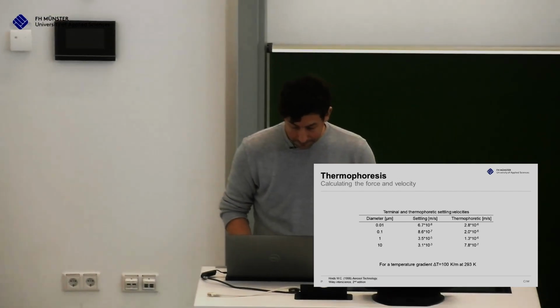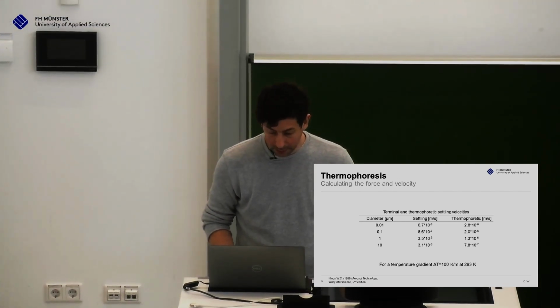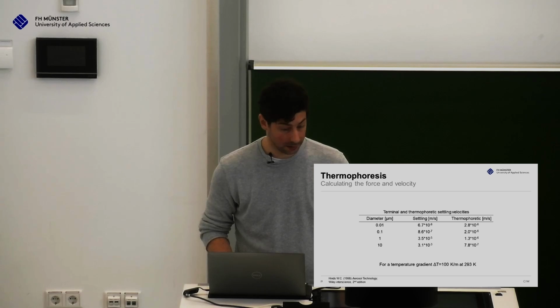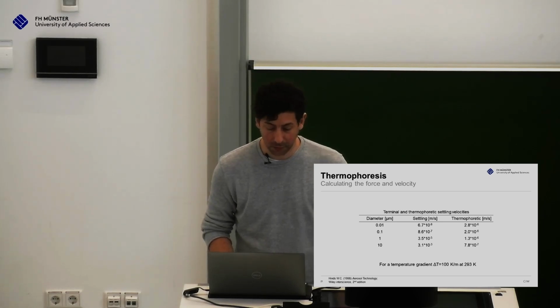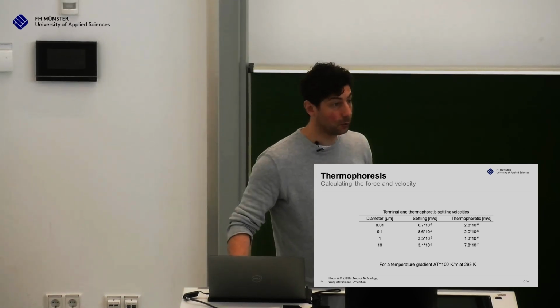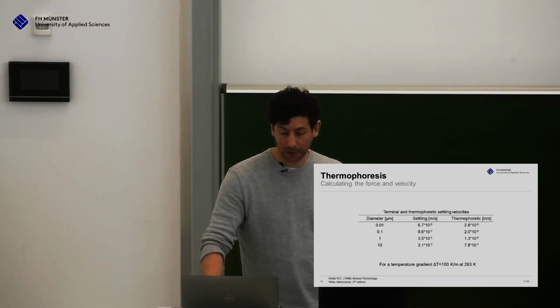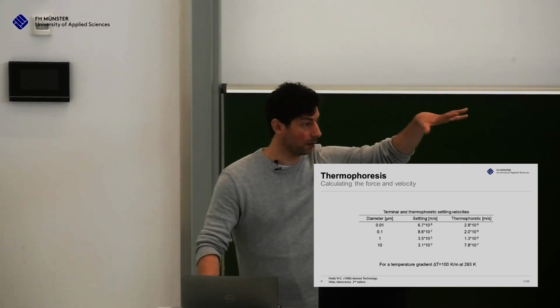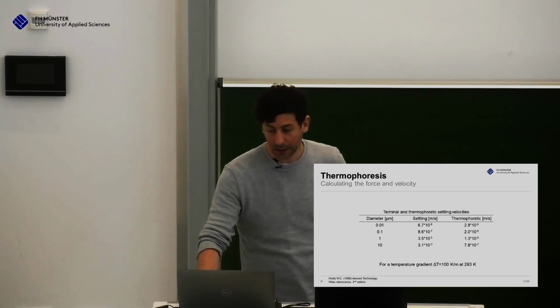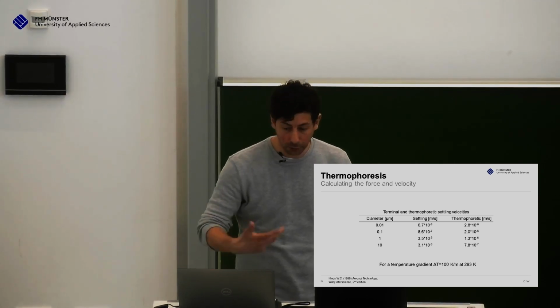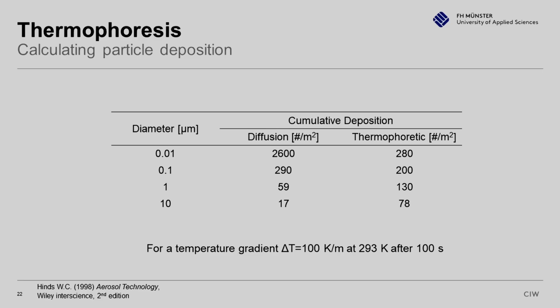And here you see that the thermophoretic velocity is quite comparable in these regimes here, okay, to settling. The settling here doesn't happen, so here the thermophoretic is much, much higher. And this is what we know. Settling is important for large particles, but for smaller particles, we cannot rely on settling. So we have thermophoretic, and the other one is, as you mentioned, diffusion. And here you see diffusion compared to thermophoretic. And this is not in terms of velocity, but in terms of particles deposited per square meter.